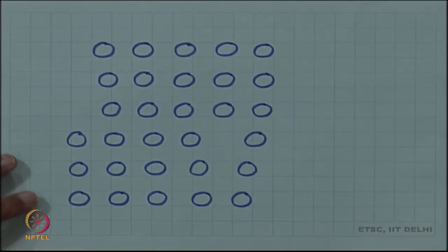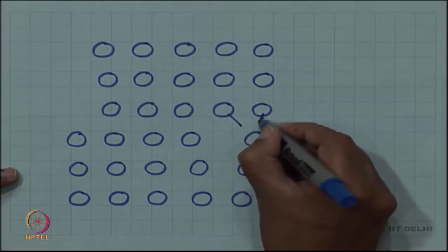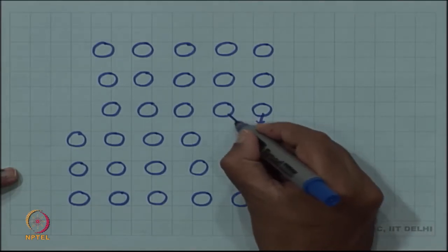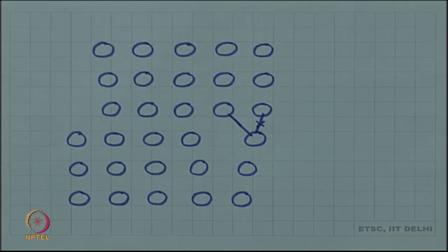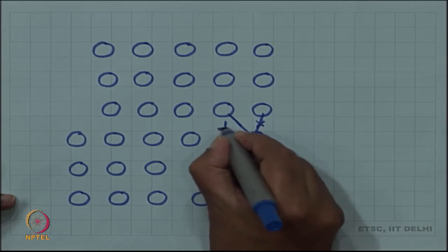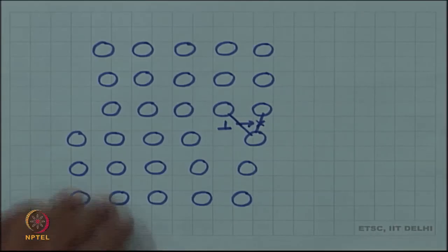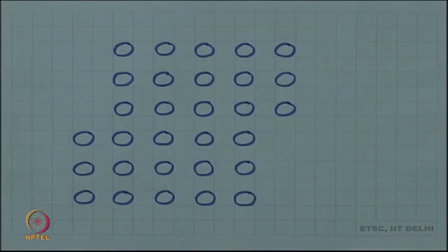Now, there is only one external plane left outside, and once I break this bond and connect it here, then this half plane will move out, the dislocation will be moving out of the crystal, and we will create a unit step in the crystal. So, this is the final arrangement where the extra half plane has now come out of the crystal.